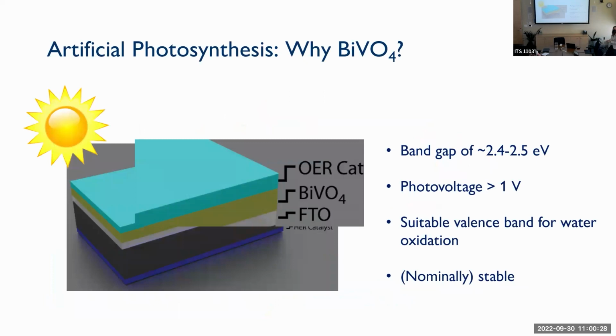This material can be bismuth vanadate. It was a thoughtful choice. Bismuth vanadate can give you more than 1 volt. And you can use this material to oxidize water. It has a band gap of 2.4, 2.5 eV. The band gap tells you about the wavelength that the material absorbs. And it has a suitable valence band for water oxidation, remember the upward band bending that I showed you earlier.